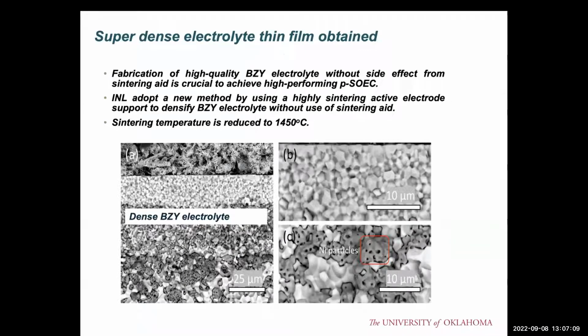This shows the sintering result. As you can see here, the electrolyte is very, very dense. As figure B shows, this electrolyte layer consists of different grains together, and we want these grains to be as big as possible. We also examined using TEM, scanning from the electrode layer to the electrolyte layer, to see if there is any element diffusion from the electrode to the electrolyte, and we demonstrated that it's pretty clean. Because of this clean electrolyte, we have no contaminant, so we can achieve the intrinsic conductivity for these materials.